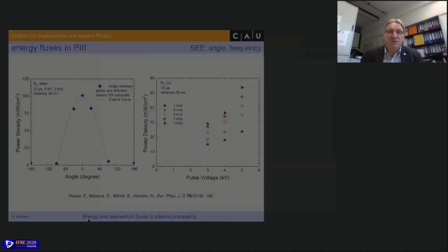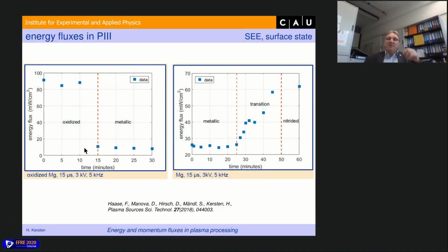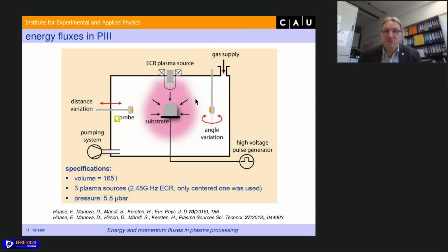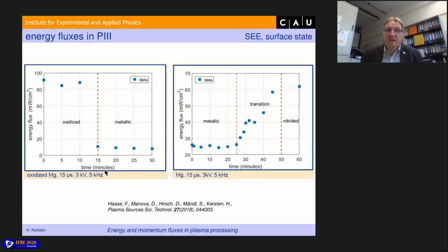But what is more interesting is that we can really measure by this method the secondary electron emission. So you can imagine if you pulse your substrate and the ions are accelerated to the substrate, then a high percentage of secondary electrons is released, and these secondary electrons are accelerated far away from the substrate, and they hit also our probe, these high energetic secondary electrons. And that we can see here.